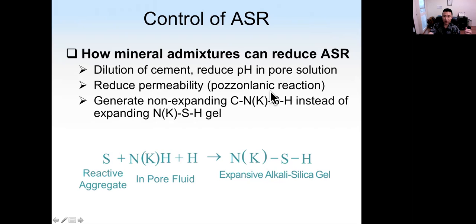And we know pozzolanic reaction will also reduce the permeability of concrete. So the water will have a harder time to penetrate and cause the swelling. So that is also beneficial. And the third reason is because mineral admixture will generate non-expansive calcium, sodium, or potassium silicate hydrate instead of expanding sodium silicate hydrate. So make the gel non-expanding. Okay. So three reasons we use mineral admixtures to control ASR.